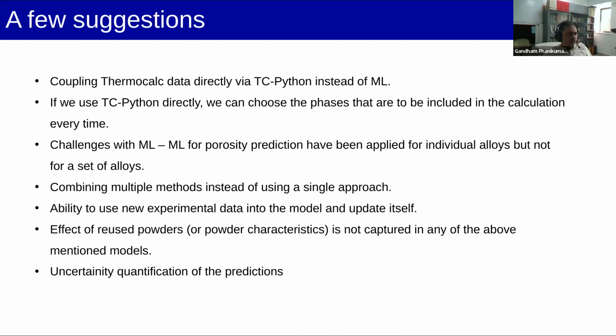And you can also do it for individual alloys, but you cannot do it across alloys, because you know that the properties of titanium alloys change quite drastically when you go from, let us say, alpha alloys to alpha beta alloys to metastable beta alloys and so on, because individual alloying elements play a big role in the segregation behavior and the liquidus temperature and so on. So therefore, we have to apply these concepts only for specific alloys.